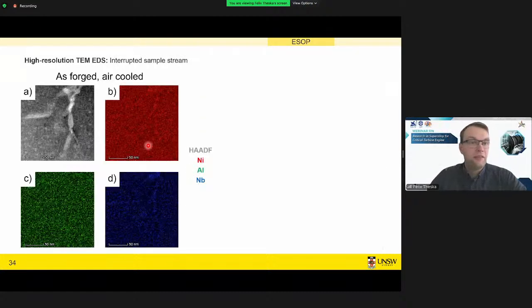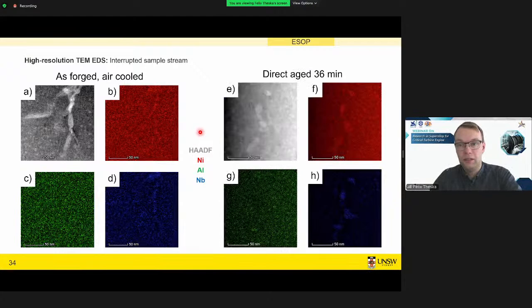While we have these samples in the TEM, we can also do some TEM EDS. In the as-forged condition, there's very little segregation occurring. What we see at all are some indications of nickel and niobium along these coarser structures. And after 0.6 hours direct aging, that's 36 minutes, we see quite clear segregation along these coarse structures, as well as along these smaller particles.